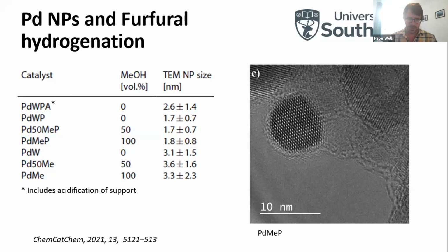And what we also found when we used methanol as a solvent, in the absence of acidification, is you can see this halo around one of the particles. This here is quite a large particle, but it does show the effect quite well. So there's something quite significant that's adhered to the particle, and that's actually the capping agent.